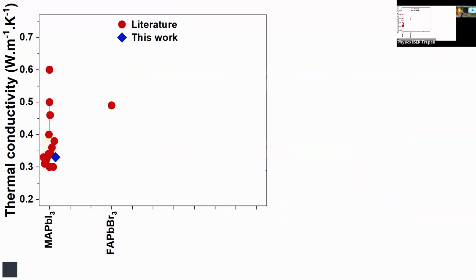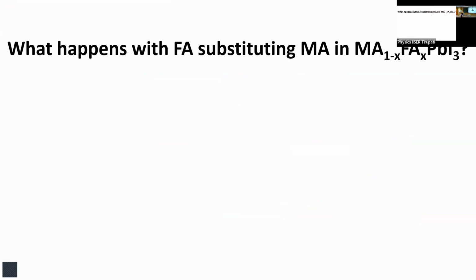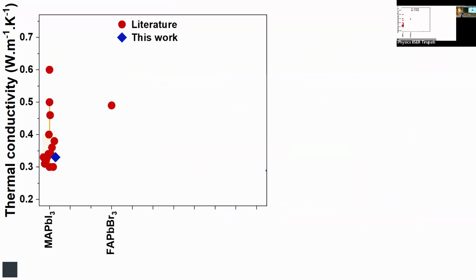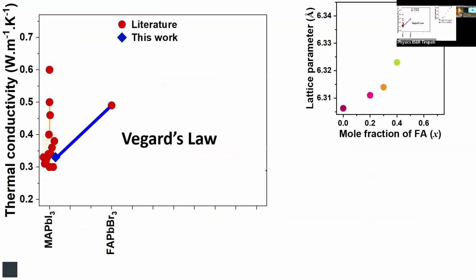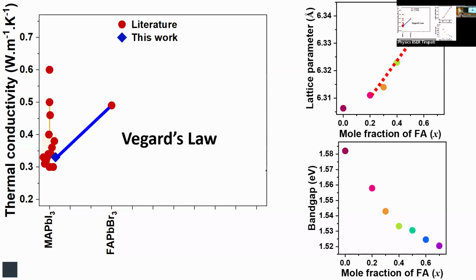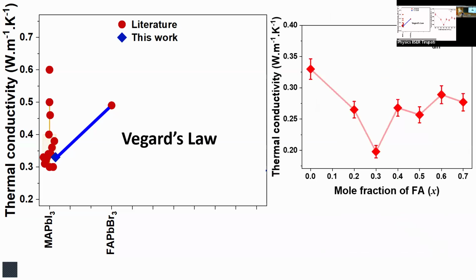But what happens if I dope FA in this? See, I can dope MA and dope FA. FA also will rotate. And then a funny thing happens. If you make a solid solution MAFA, you would expect physical properties to evolve linearly. That's called Vegard's law. For example, the lattice parameter of this MAFA composition is changing almost linearly. This one I leave out because there's a change in crystal structure here. Lattice parameter evolves linearly. Band gap evolves linearly with fraction. But the thermal conductivity has a non-monotonic behavior. And there's again a puzzle that is very difficult.